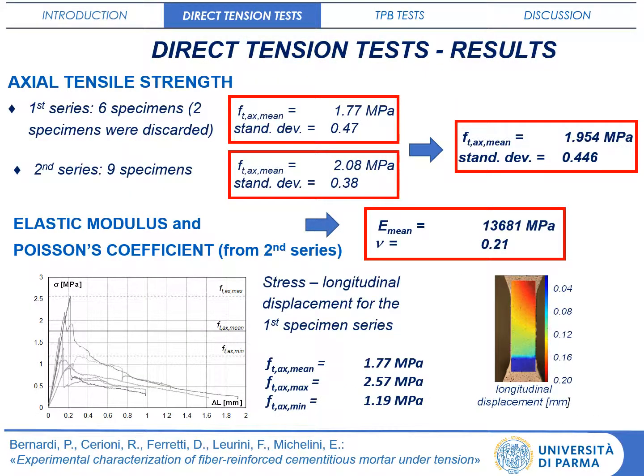By considering the cracking loads, a mean value of tensile strength is provided. It can be observed that this kind of direct tensile tests seem promising also for cementitious mortars, even if it requires special care to avoid bending, scatter results and anomalous crack formation.